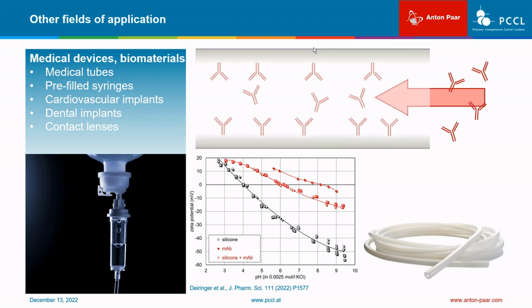When we pass the aqueous solution that contains the antibody through the silicone hose, and when we record the Zeta potential simultaneously, we realize a shift of the Zeta potential towards less negative values and an increase in the isoelectric point compared to the results for the pristine silicone tube. A significant fraction of the antibody is obviously adsorbing on the hydrophobic silicone surface. We estimate a surface coverage of approximately 50% from the locations of the corresponding isoelectric points.